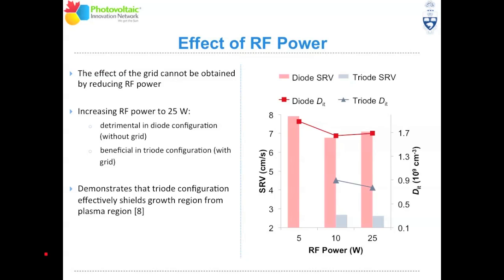So this is one example where we varied the RF power, and in the diode configuration, as you can see, as we changed the RF power from 5 watts to 25 watts, we didn't get very much change in terms of the surface recombination velocity. Actually, when we went down to 5 watts, we actually got even higher surface recombination velocity. So the passivation quality actually deteriorated a little bit.